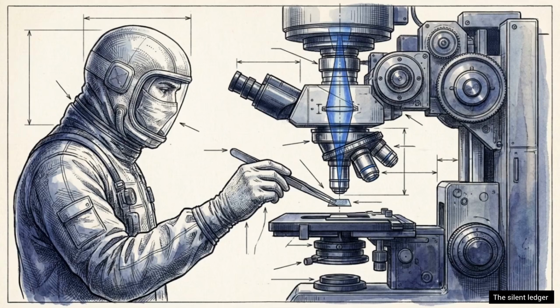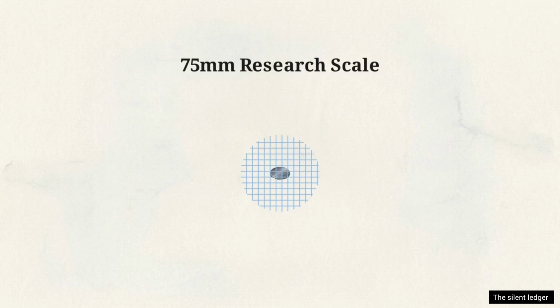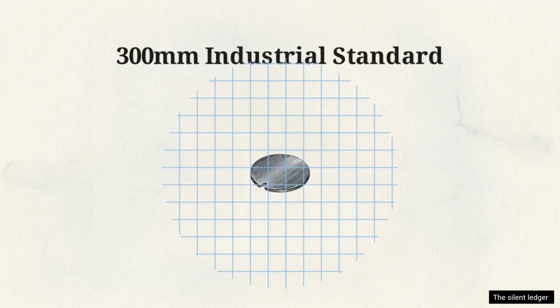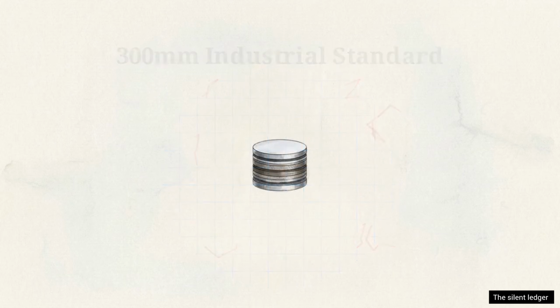However, this process is currently a laboratory demonstration. High-volume commercial manufacturing remains unproven, and the scale-up barriers are significant. The physical challenge is scale. Proved on a 75mm research wafer, transferring flexible membranes perfectly across a massive 300mm industrial wafer is a severe engineering hurdle. Also, packing active devices vertically introduces a concentration of trapped heat deep inside the 3D stack.